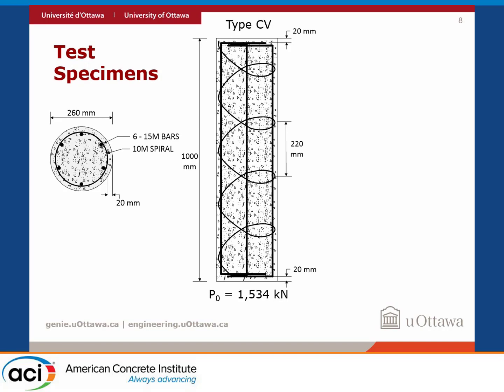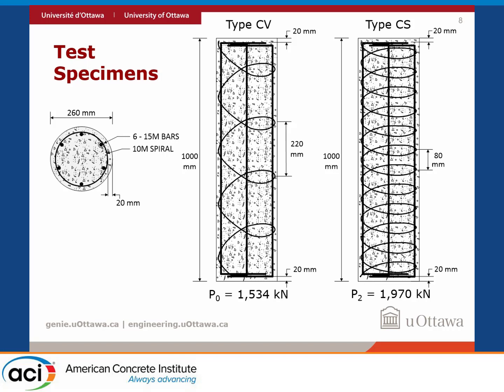And the other type of columns that we had, so we have 5 of CV and 5 of CS. The pitch was 80 millimeters, which corresponds to the minimum confinement provided. And we calculated the second peak due to that confinement as almost 2,000 kilonewtons.